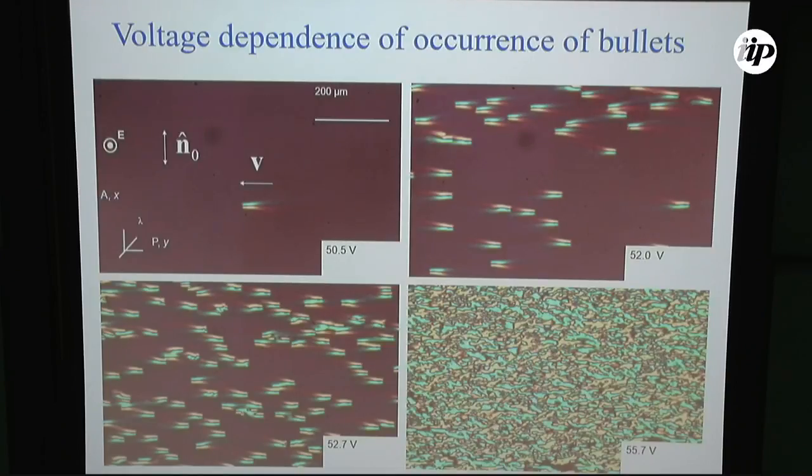Well, not in details. We understand, in general terms, that when you collide two director perturbations, they need some time to reconstruct themselves, and that time depends on the viscosity of director reorientation. We know the numbers there, and we know how long it would take, and it appears to be consistent with the observations, but we don't have the exact theory even for the single soliton existence, not even going to the issue of their interaction.